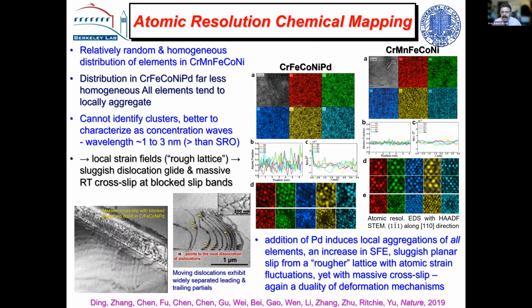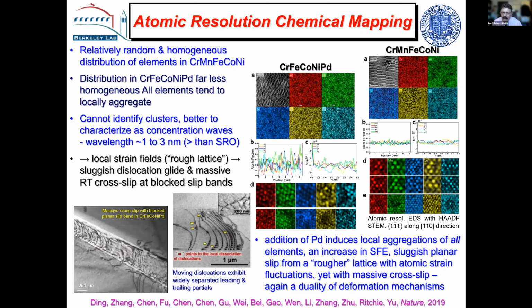And so it's difficult to say that this is actually clustering. These are concentration modulations which have some degree of periodicity. The wavelength is about 1 to 3 nanometers, which is much higher than the normal short range order, which is basically nearest neighbor shells, but it's clearly a form of ordering, and it generates a rougher lattice.